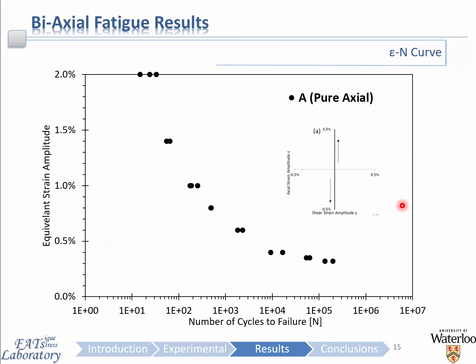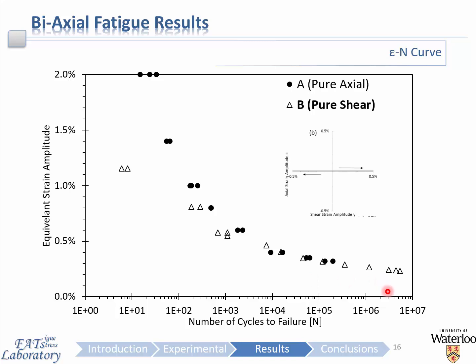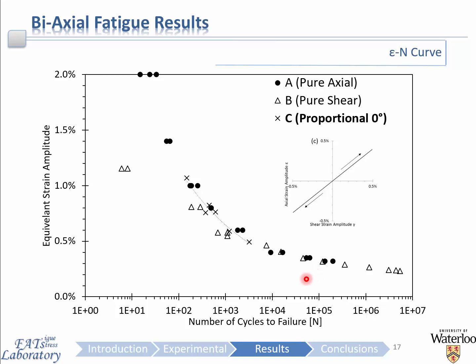Now, to summarize the strain life curves for each of these cases, this slide illustrates the pure axial behavior. So this is strain amplitude on the y-axis versus number of cycles to failure on the x. Here is the pure shear behavior with the von Mises equivalent strain amplitude being graphed on the y-axis as shown. It can be observed that in the high cycle regime, the behavior between pure axial and pure shear is virtually identical. Now, adding the proportional biaxial cases, it can be seen that they behave somewhat as one would expect, as an average of the axial and the shear responses, so it's somewhat in between these two curves here.